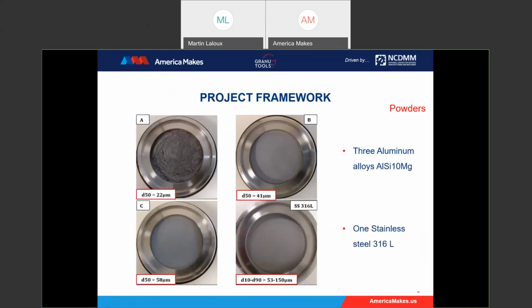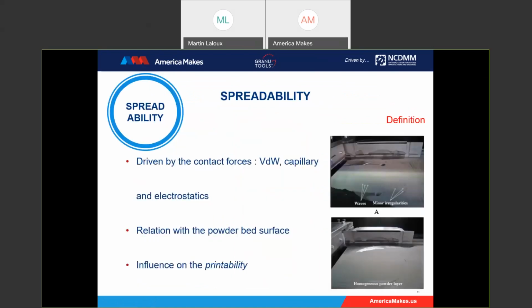So here are the 4 powders we studied: 3 aluminum alloys, samples A, B, and C with different D50. The A sample has the lowest, finest particle size, then B, then C, and we have a stainless steel powder. So to go through the first parameter we studied, the spreadability.